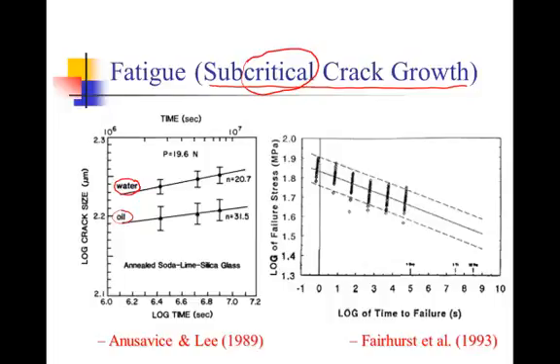And another experiment was conducted at Medical College of Georgia by Dr. Carl Fairhurst. He took ceramic bars, dental porcelain bars, and had a testing machine slowly bend them until they fracture. So he applied stress that was increasing slowly over time and measured the average strength at which the dental porcelain failed. And you see that as he measured it, there was a distribution among the porcelain specimens. They didn't all have the same strength because they started with different sizes for the largest flaw in each one.